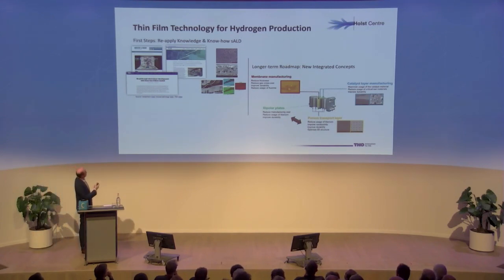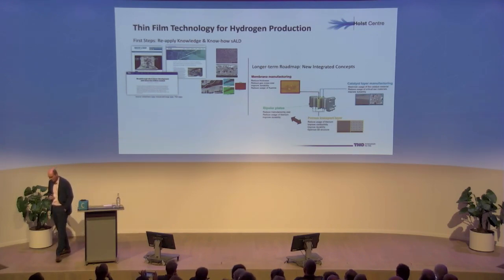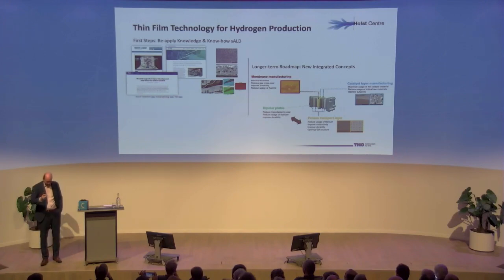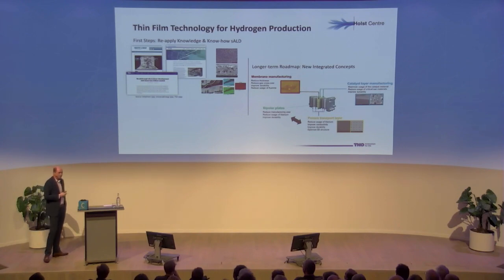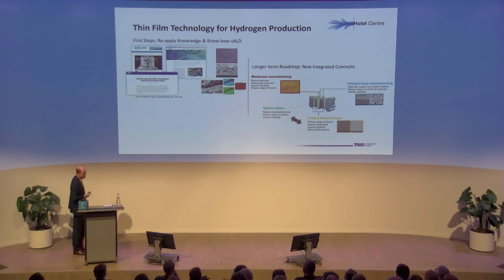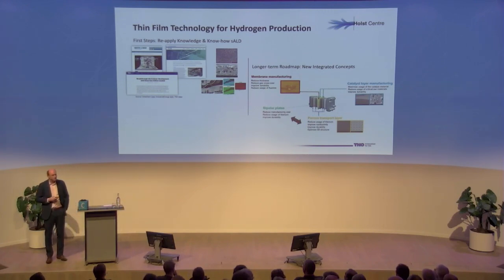So actually we decrease the use of iridium. Iridium is used as the catalyst in hydrogen production. So at the surface, you need minimum amount of iridium to actually do a right proper conversion of water into protons. But because if we now have the plans for 2030 for all the hydrogen that we want to install, we need 250% of the amount of iridium that is yearly produced. So if we can significantly reduce that use, we are doing our best for the climate change.